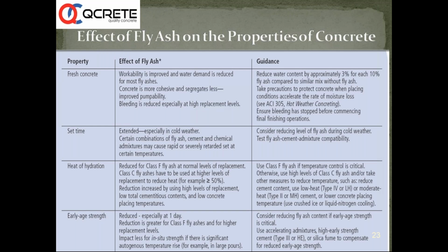Early age strength: the entire reaction takes place in two stages. One is cement plus water forming CSH gel and calcium hydroxide. Second, the SiO2 and other components of fly ash react with the hydrated products like calcium hydroxide, consuming calcium hydroxide and forming some more CSH gel. So there is a time lag, and hence early ages are affected and reduced, especially at 1 day. So we need to take care of this.